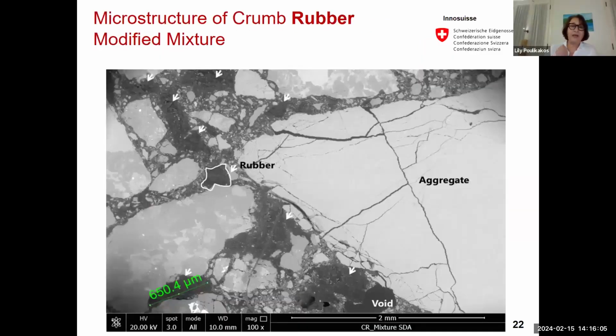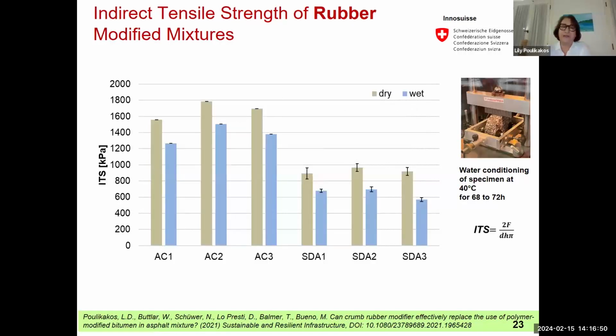Again, this is an electron microscope image of a crumb rubber modified mixture. You see the different elements of our mixture that are present. You see the aggregates, you see the mastic with filler. However, there are also pieces of rubber that are still in our mixture. So why is that important? Well, when our mixture is cold, everything is behaving elastically. However, once the temperature goes up, our bitumen becomes viscoelastic. However, the rubber remains elastic. This difference also adds to the performance.